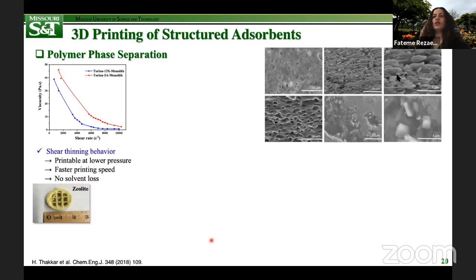Looking at the viscosity shear rate profiles here, I'm showing you the two polymer sorbent pastes prepared for extrusion. We noted that higher shear rates displayed good flowing characteristics, which means low viscosity, whereas a high viscosity is obtained at low shear rates. So these results are generally indicative of a good extrusion behavior. In other words, low viscosities at high shear rates for both polymer sorbent pastes investigated in our preliminary investigations.